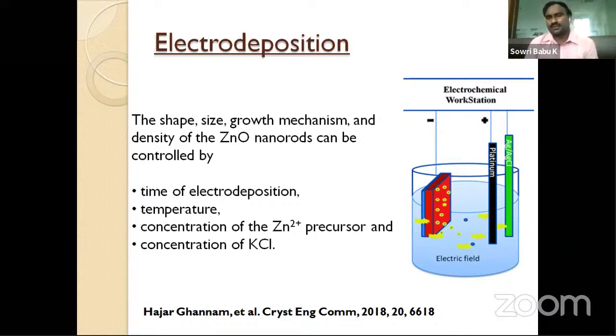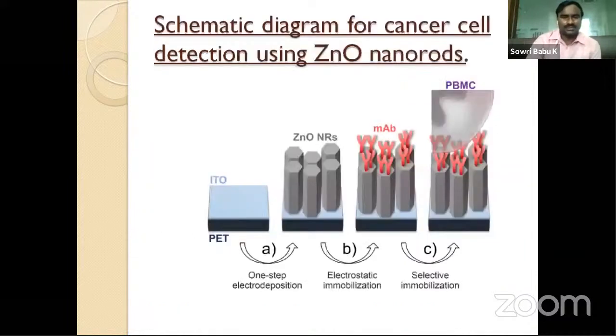So in the process of electrochemical oxidation, we have a reference electrode and a counter electrode, that is, a platinum counter electrode, and the working electrode will be our ITO on the PET. Okay. So we can have a zinc oxide film if we do the electrodeposition process at room temperature. Suppose we increase the temperature to around 80 degrees centigrade and keep it there, then we have the growth of nanorods. Very simple.